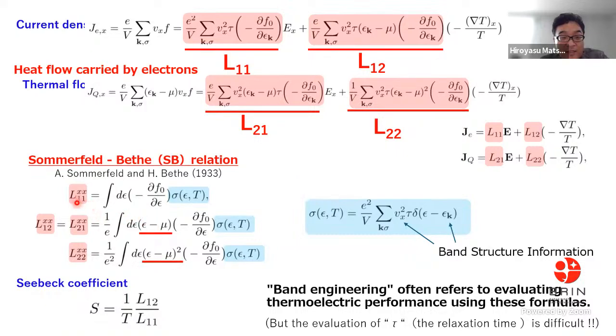The important point is that these L coefficients can be expressed by the same sigma. This sigma comes from these equations, where v is the velocity of electrons, tau is the relaxation time, and delta is the delta function. So if you know the function sigma, you can calculate L11, L12, L22, and get the Seebeck coefficient, the thermal conductivity, and ZT. Band calculations give the information of v and epsilon_k. If you use, for example, a constant tau, you can get sigma, then use this equation to get the L's and the Seebeck coefficient. This is band engineering studies.